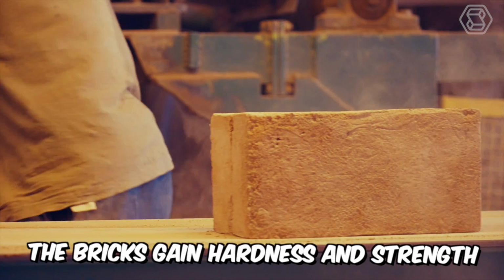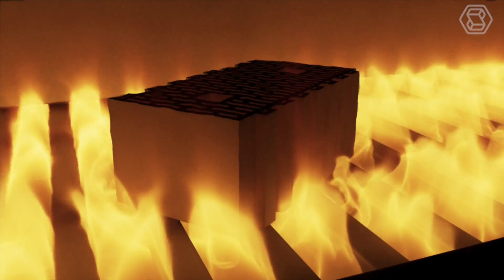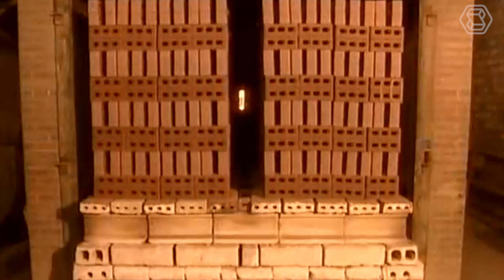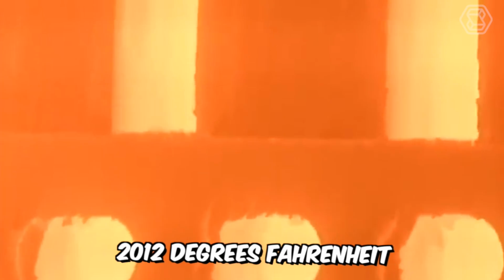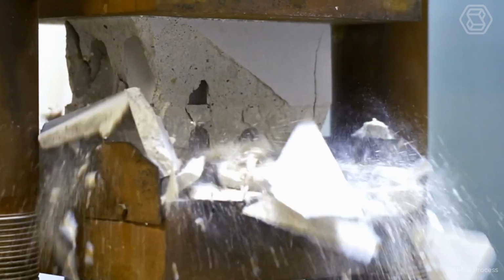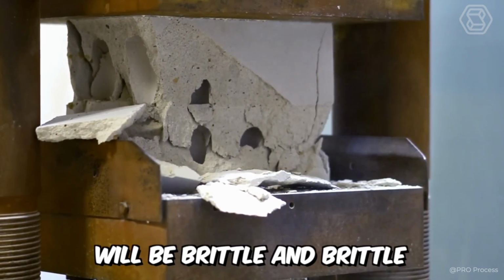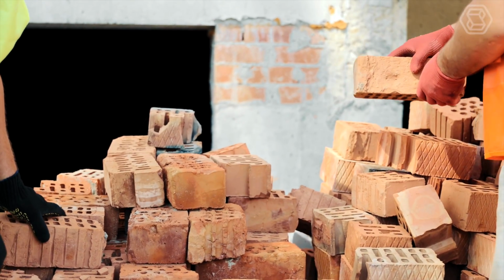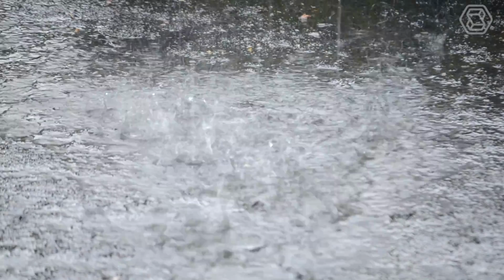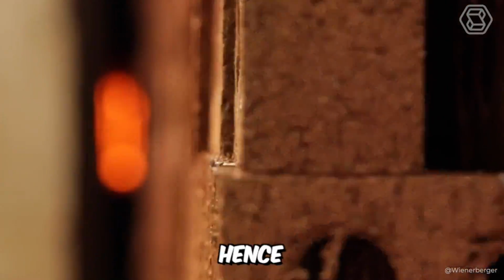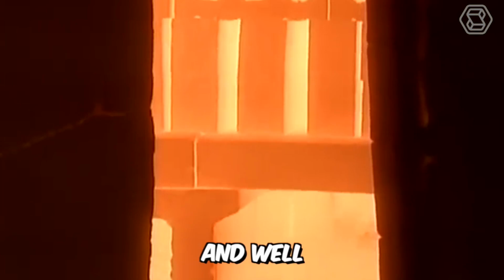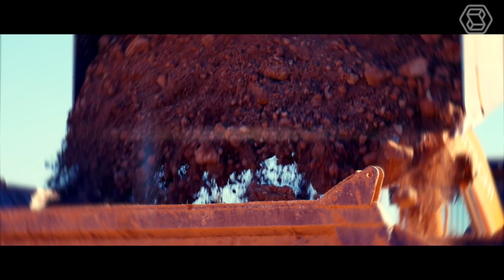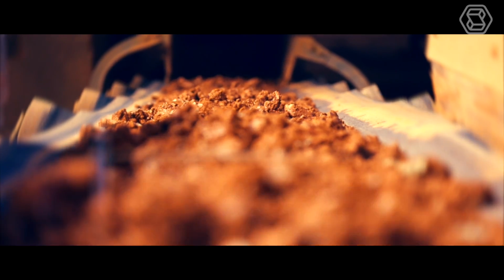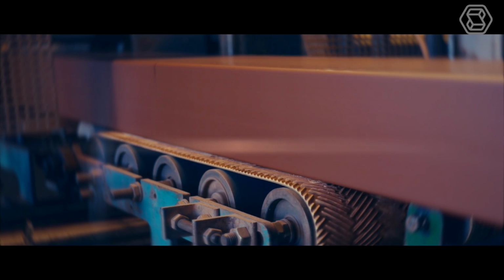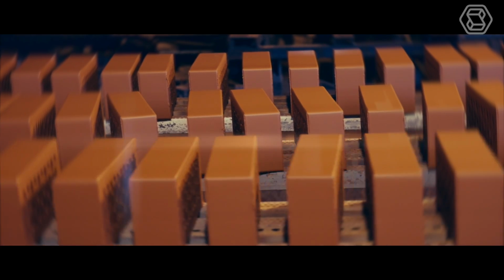At this stage, the bricks gain hardness and strength, so it's an important stage in production. The temperature required for combustion is about 2012 degrees Fahrenheit. If they burn beyond this limit, the output of the finished product will be brittle and weak. And if the temperature limit is lower, the bricks will not gain full strength and are likely to absorb moisture from the atmosphere. Hence, the firing must be done properly and well to meet all the requirements of a good brick. As you can see for yourself, the production process is quite complex and labor-intensive, but at the same time, it's interesting and diverse.